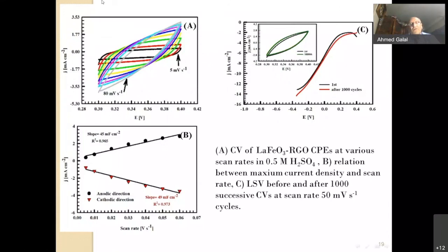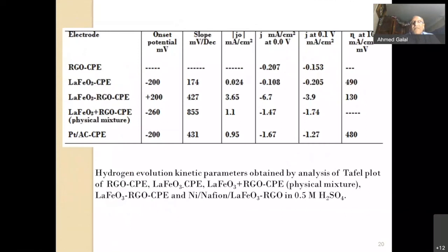And we have also examined the effect of scan rate, just to examine whether we have a diffusional process at the interface. This comparison here compares the different surfaces in terms of the onset potential, and as you can see here, a positive value for this particular catalyst, but surprisingly enough, with a very high Tafel slope, but with a reasonable exchange current density, and also with the current density at zero potential, and at about 0.1 volt, and at 10 milliampere, what was the amount of currents obtained, just for the comparison of the performance.